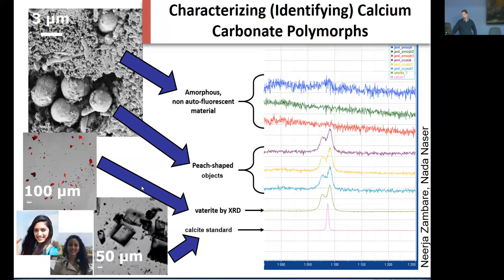But what Raman has shown us: we were able to zoom or focus on these peach-shaped crystals, as well as on this more amorphous material. For the amorphous material, we don't get a whole lot of the Raman spectrum. For these objects, we got something in the range of 1083, which is characteristic for carbonates, but there was kind of a double peak. So you can see them here.